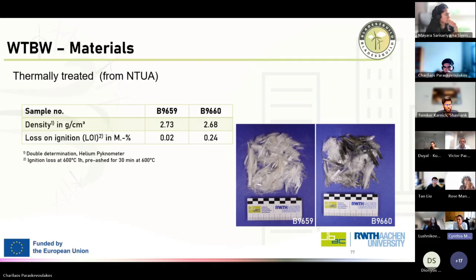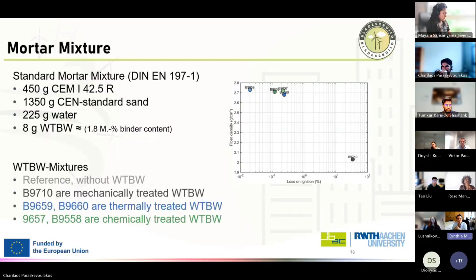And just keep this in mind because we integrated these fibers into our standard mortar mixtures, and then you will see that there are some variations. And this slightly has to do with the materials that we received. So everything that we received here at IBAC was used exactly as produced. We did not do any further processing of these materials in any way. So if we go to the next slide, please, you will see the mixture that we worked with. We based our studies on the standard mortar mixture according to DIN EN 196-1.